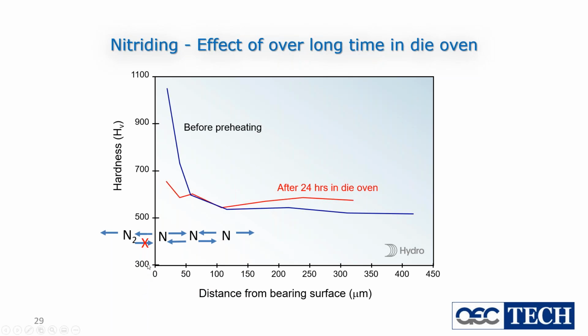Oh, there's my little nitrogen moving backwards and forwards on this one. So the nitrogen near the surface, if it diffuses inwards, it can move backwards and forwards in here, and some of it goes deeper. The nitrogen at the surface of the steel, it comes out and there is no way back, because now it's an N2 and it can't fit. So the way we treat our dies after we've done our nitriding is very important.